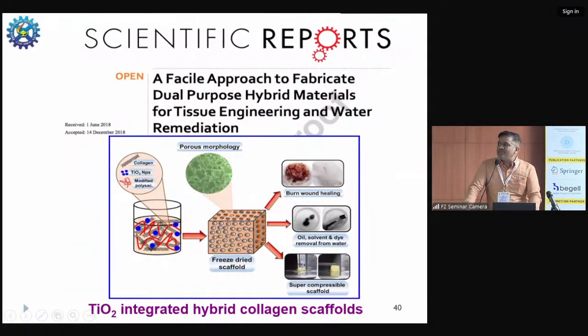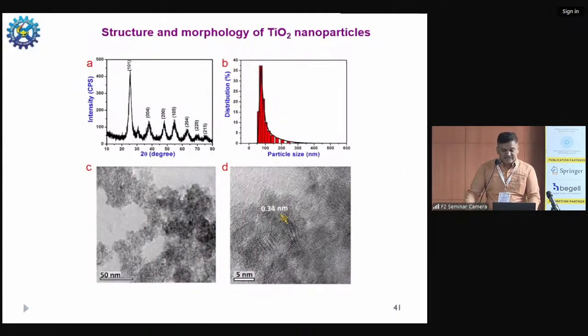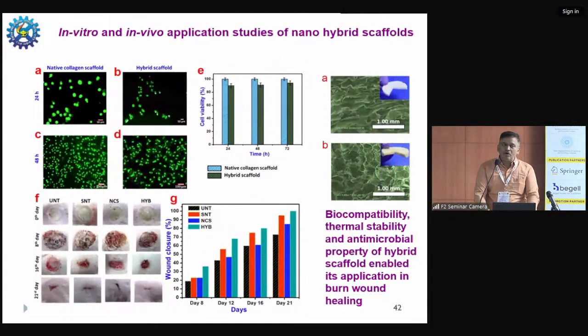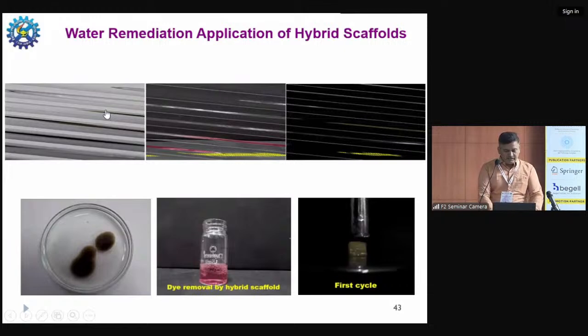In this example, what we try to show is that we incorporate titanium dioxide (TiO2) nanoparticles and develop a kind of dual-purpose hybrid material for both environmental and biomedical applications. We initially prepared the titanium dioxide (TiO2) nanoparticles, which are anatase structure, incorporated them into the collagen, and developed the spongy material. We show that this can be used as a scaffold even for burn wound healing applications, where at the end of the 21st day our scaffold has very good closure of the wound. And this can also be used for the removal of dye.